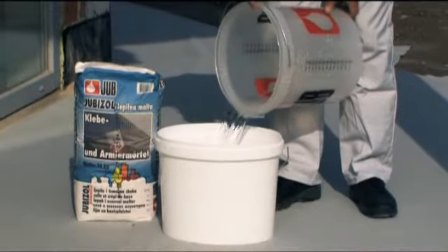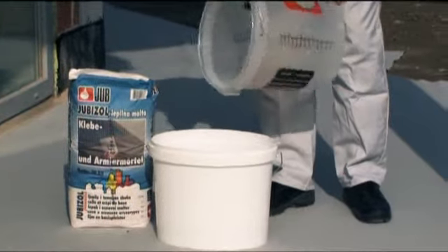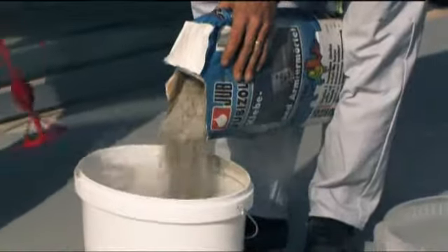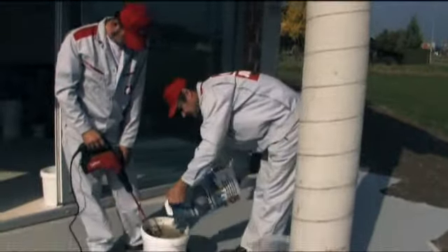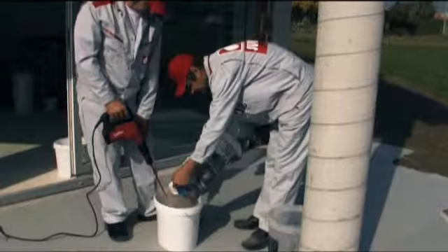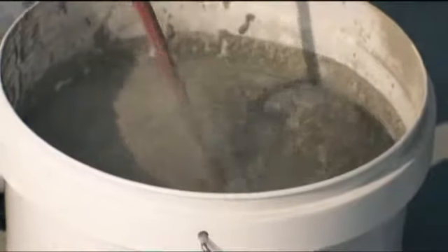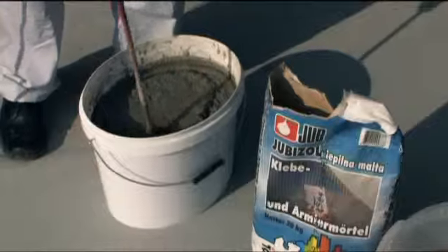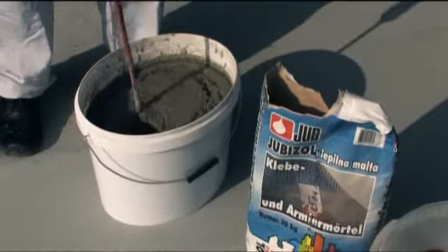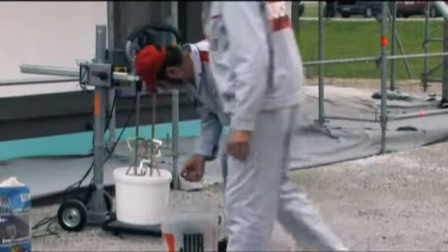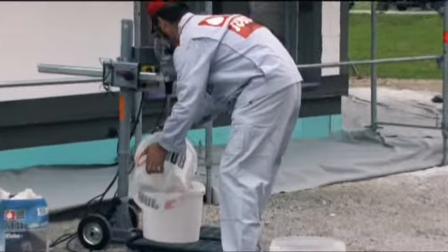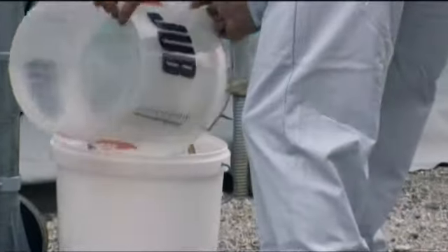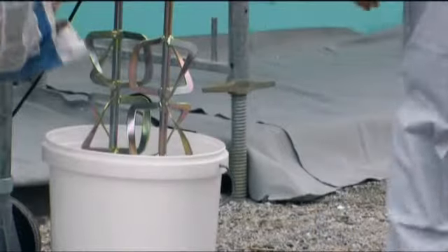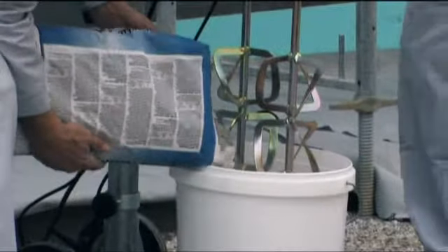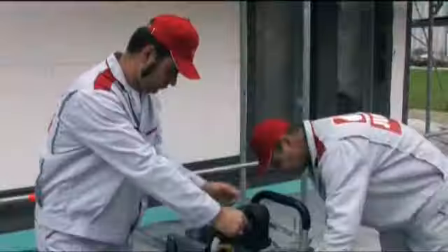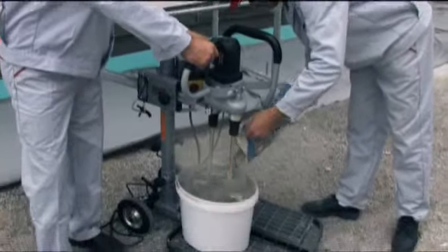Any Jubizol adhesive mortar or mortar for the base coat can be prepared in a concrete mixer, but most often it's mixed with an electric mixer in an appropriately sized plastic bucket. Start by pouring about 20% of water by volume of dry compound into the container for the preparation of the adhesive. Then pour the adhesive in powder form into the measured quantity of water. Stir well and leave for 5 to 10 minutes and allow the compound to rise. After that, again stir the mortar compound well, and only if necessary add a little water or adhesive powder.